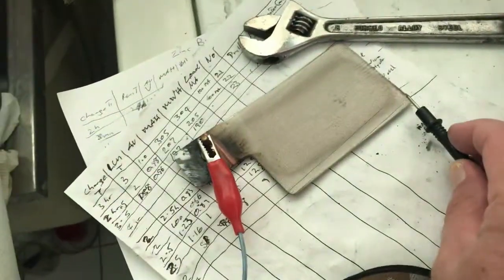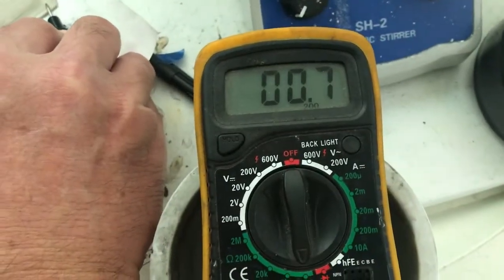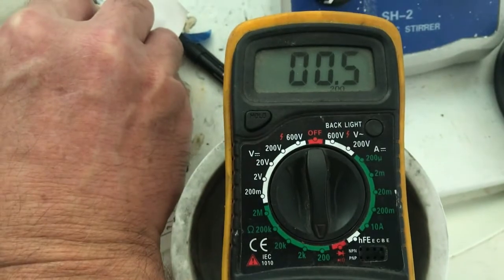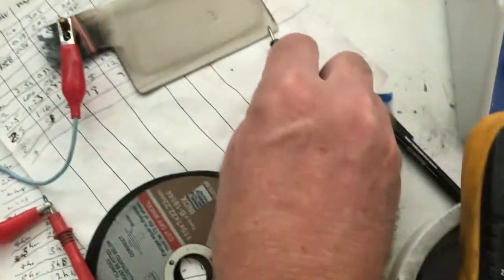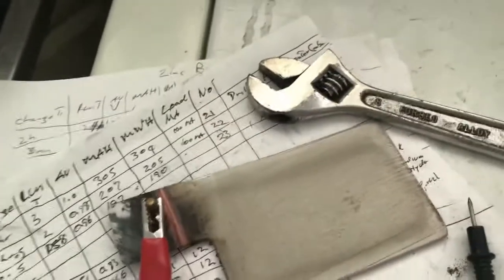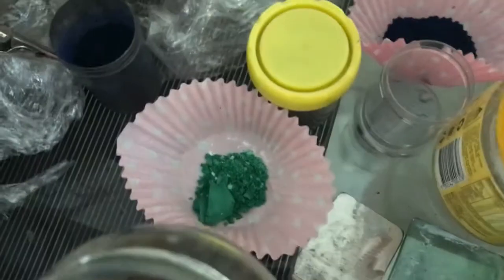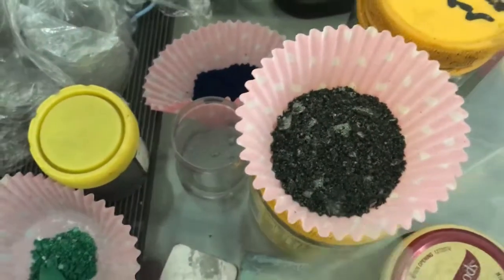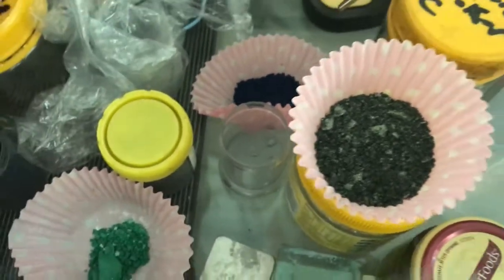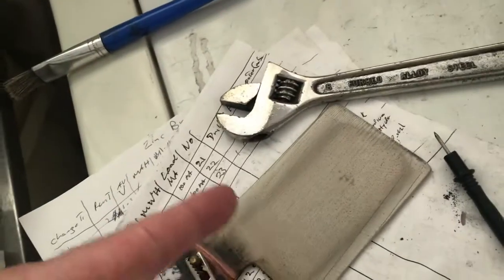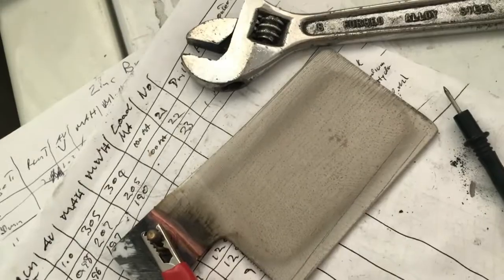Now the resistance from the brass lug to here is, on the 200 range, 0.5 ohms, which ain't too bad, pretty good, that should do. I'm going to use this mesh to sieve the nickel oxyhydroxide, should say nickel hydroxide, and the nickel hydroxide in little bits of carbon as well. I think there's 10 grams there, 5 there. So I'll just coat it with a brush and the conductive ink and sprinkle some of that over both sides of that plate.